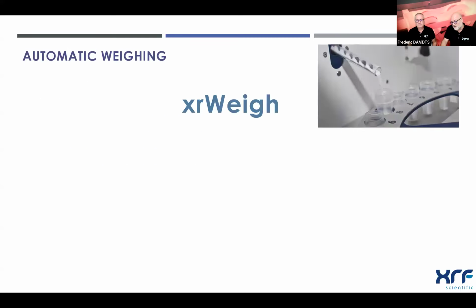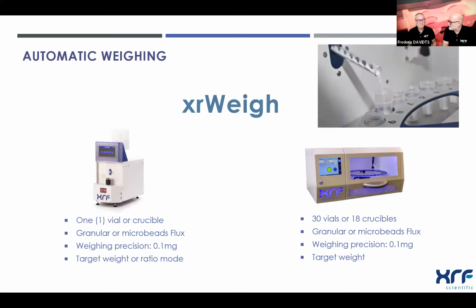So automatic weighing, of course, is most used when you have a lot of samples to do per day, to let a machine do a boring task for you. And we have for that the xrWeigh carousel with 30 positions, 30 vials, but also for health reasons. And as you know, the fluxes are not the best chemicals for the operator, and so it's good to have a machine that avoids the chemist being too much in contact with the flux. So just put the crucibles and the machine does the rest. So it allows you to keep away. And of course, you have a better repeatability because you avoid human errors in the weighing process.